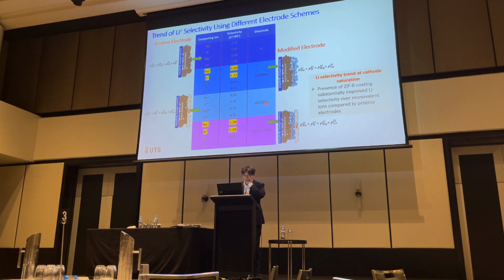We compared these results and found that when you have only electrodes, there is not much lithium selectivity compared to other ions like sodium, potassium, magnesium, and calcium. However, when you put ZIF on top of the activated carbon, we increase the overall selectivity up to 3.08 for lithium to sodium and 1.12 for lithium to potassium. Then when you use only the cation exchange membrane, we were not able to find any selectivity increase.